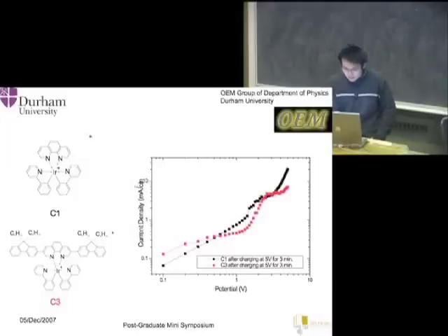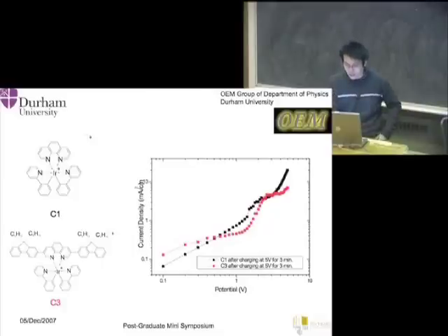So we're thinking that maybe this first turn-on is, okay, before 1 volt, it's still an insulator, right? After that, because the ion, the PF6, begins to flow, you feel the current at this time. But because this current is caused by the ion, there is no light coming out. After about 3 volts, there is another increase. This is the injection from the cathode and anode. From here, we begin to see the light, which is very true when we look at this other curve.